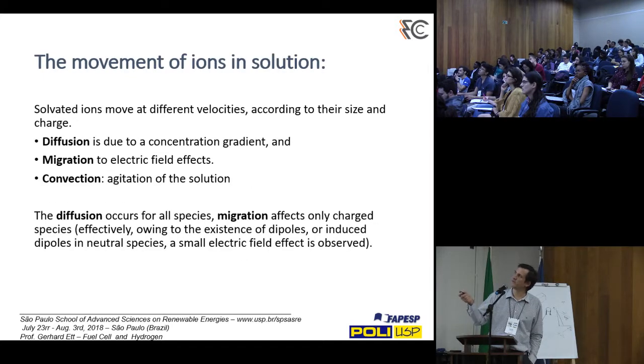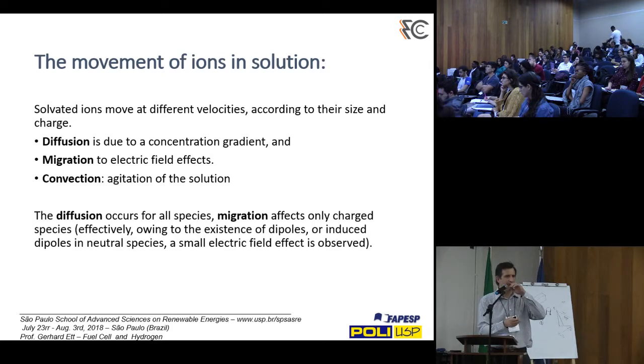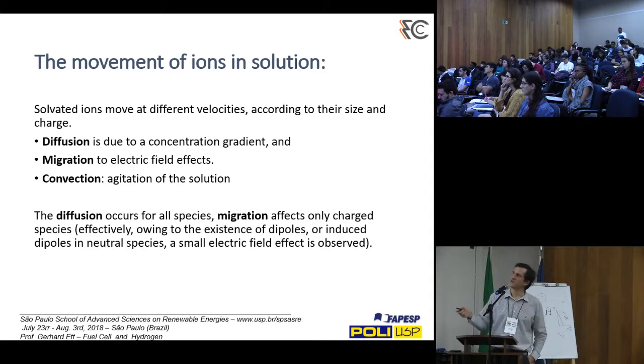Here we have the movement of the ions in the solution. Diffusion is due to the concentration gradient. With a difference of concentration, you have diffusion of the element from where you have more concentration to low concentration. Migration is where you have an electric field effect. You have something like a magnet. If you have more electric effect, you have more migration. Normally this happens nearby the electrode, not in the area where you have diffusion, but very near the surface of the electrode.